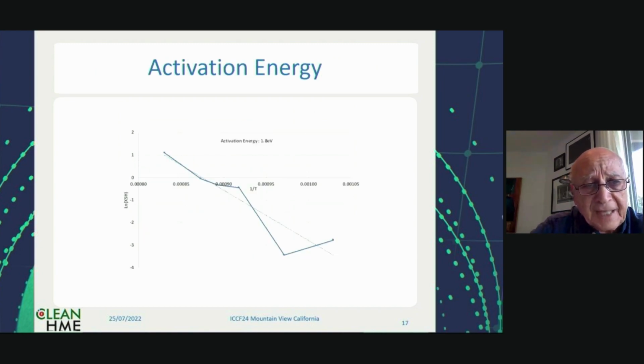Out of that, we can calculate the activation energy because we have the excess heat versus temperature. It's not very precise, obviously, because of the error bars, especially at low power, but that gives you an idea of the activation energy, which is not very different from what Ed Storms is measuring.